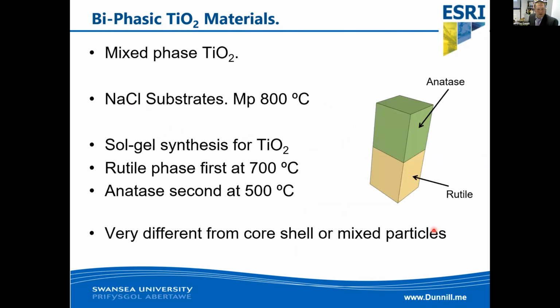So a nice example here is to take some titanium oxide as mixed phases. We take a sodium chloride substrate with a melting point of 800 degrees. We can do a simple sol-gel synthesis, which gives us TiO2. And if we anneal that at 700 degrees, we end up with the rutile phase. If we then apply anatase on top by doing the same sol-gel synthesis, but this time at 500 degrees and not holding it for too long, we end up with these Janus particles.